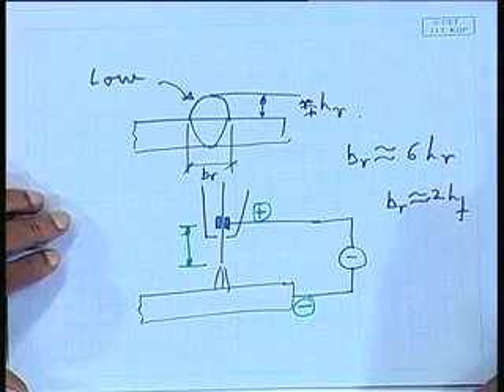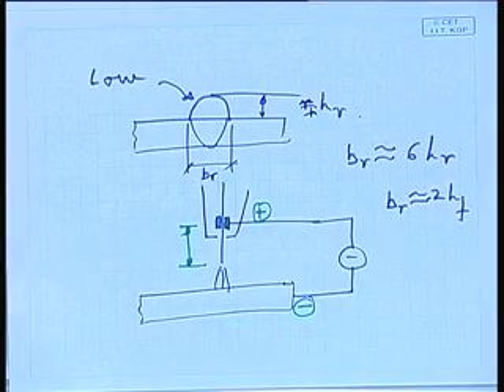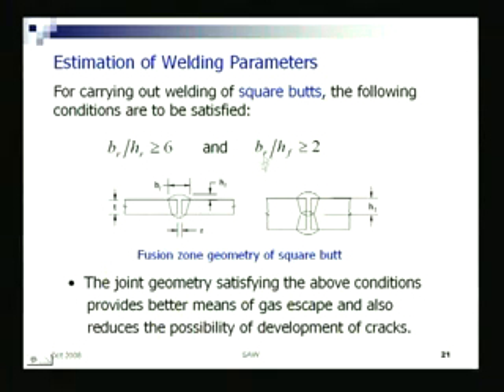If that can be achieved, then generally cracks will not form. The joint geometry satisfying these above conditions provides better means of gas escape and also reduces the possibility of developing cracks.